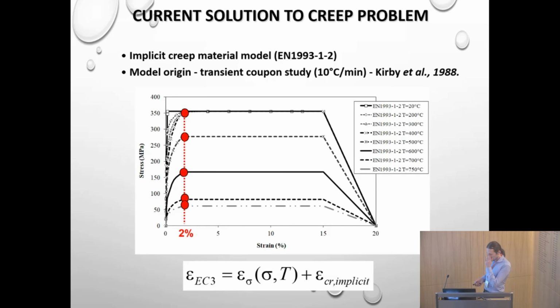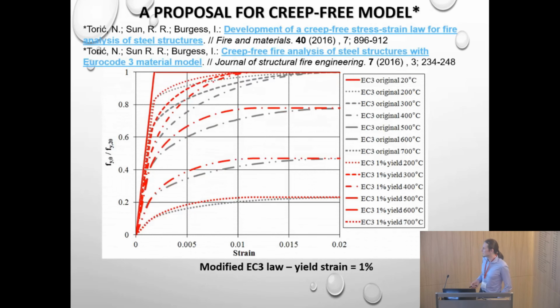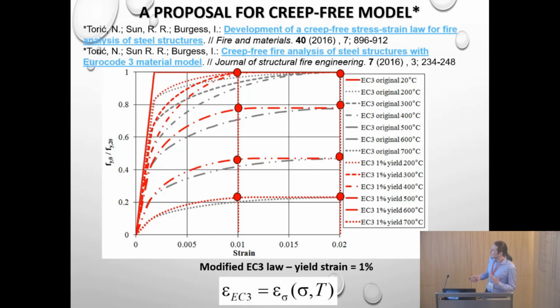So the first thing that we didn't have is basically what's the mechanical stress strain relationship without this implicit creep component. So before we applied for the project, we tried to remove this implicit creep strain component just to see how much creep is present in the Eurocode 3 stress strain law. So we got an approximation of a creep-free model, which is based on Eurocode, which excludes the implicit creep component by shifting the yield strain from 2% to 1%. So this is our estimate of the creep-free stress strain law, which could be used on the basis of the original Eurocode 3 model. So this was also motivation to do creep research on the behavior of steel columns, because the implicit creep component, if this is true, is very small in the original Eurocode model.